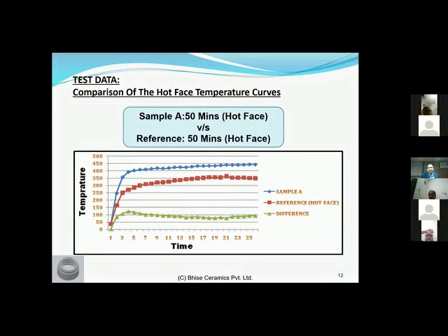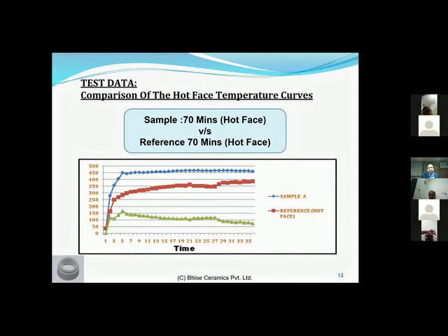Now, if you look at the 70-minute curve, it also looks fairly similar. If you see over here, round about after 7 or 8 minutes, you've started to get the plateau. You've got a minor rise over here. But on an average, where this system took about 21 minutes to stabilize, this system had stabilized in 11 minutes.